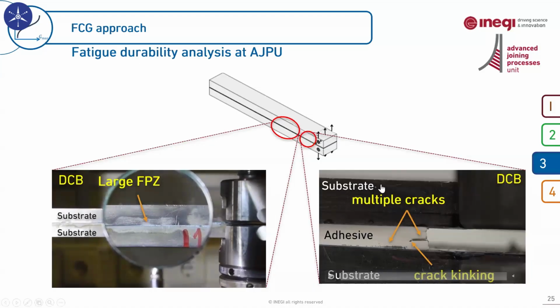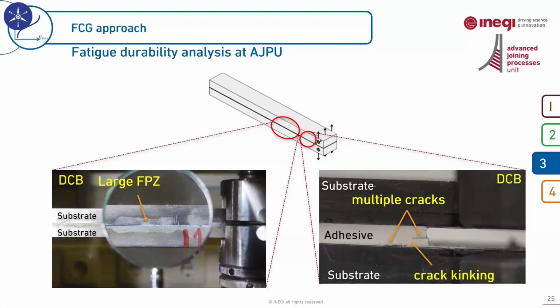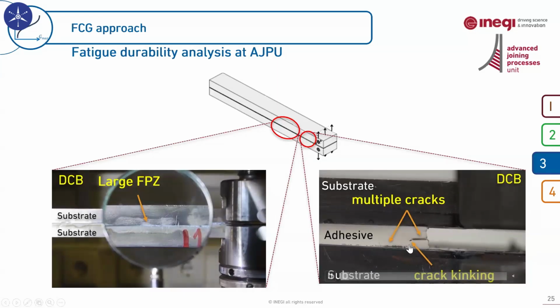On the other side, we have another DCB tested under pure mode 1 loading condition. This is not a very zoomed view. Here we have a very thick layer of adhesive, a 4 millimeter thick adhesive layer. And we have several phenomena here. We have multiple cracks. We see a secondary crack here already propagated. Another phenomenon is crack kinking. We see that this is the pre-crack, and the pre-crack doesn't propagate along the midplane of the adhesive layer, but it kinks towards one of the interfaces here.